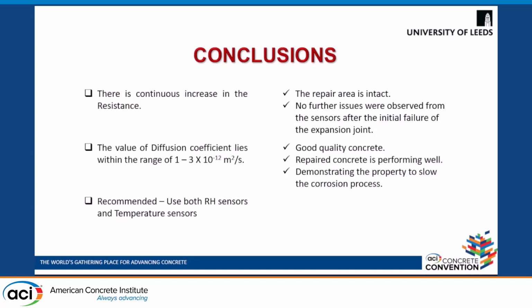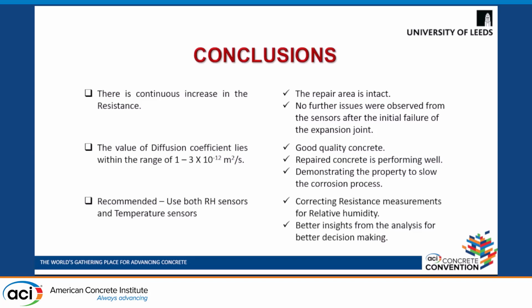And finally, it is recommended to use both relative humidity sensors and temperature sensors inside and outside the concrete, to correct the resistance temperature measurements for relative humidity and to get better insights from the analysis for better decision making.